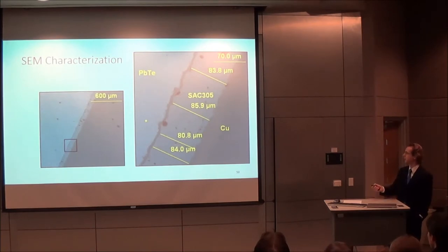And so here we have the different materials, the lead telluride, the copper. The lead telluride appears brighter because it has heavier elements, and they show lighter in these images using backscatter mode. And then the nickel-gold diffusion layer, and then the solder interlayer.